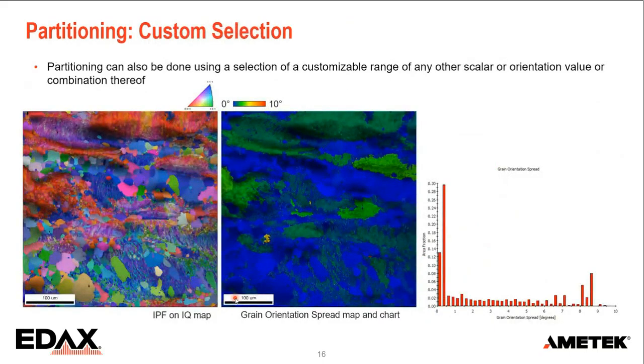Now, in some cases it can be difficult to manually define in a fixed filter what you want to do. Then you can also do a custom selection. So here I have a partially recrystallized steel. You can recognize the recrystallized grains quite nicely here with nice uniform colors and deformed areas in between, and also down here, for example. Then we can make a chart looking at the grain orientation spread.